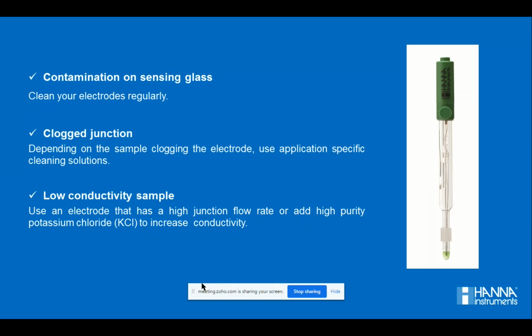So why does contamination give erratic readings? Contamination might give erratic readings, or wrong readings, slightly lower or slightly higher than expected, because of the deposition of the samples or any other material on the electrode. The millivolts of that deposition add on to the millivolts of your sample, and might give positive or negative interference in your reading. Thus, the solution or troubleshooting for this common issue is to clean your electrode regularly with cleaning solution. Whenever you calibrate a pH electrode, the meter itself assumes that the electrode is clean, and thus it nullifies the error accordingly after the calibration. Thus it is very necessary that you should have a clean electrode just before calibration.